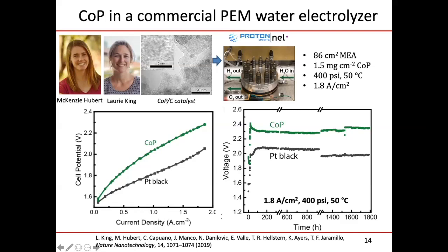They do sell this electrolyzer. It's a commercial device, but of course it has platinum and iridium in there. And so they basically just swapped out one catalyst for the other and looked at the performance. And now we're operating at 1.8 amps per square centimeter at 400 PSI, 50 degrees C. This is exactly the operating conditions of their commercial system.